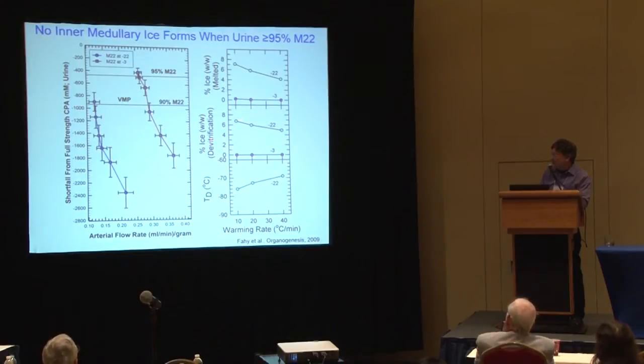And by the way, another point is that in the kidney, as far as we can measure, all ice that we see melting has been ice that formed during the devitrification process. So there's no ice on cooling. All ice is apparently formed on warming. All, meaning excluding teeny tiny nuclei, which is an infinitesimal volume fraction. I won't go into that. Okay, so that's part of the boundary condition on the problem, but we can't perfuse kidneys at minus 3 either because that would kill them too.